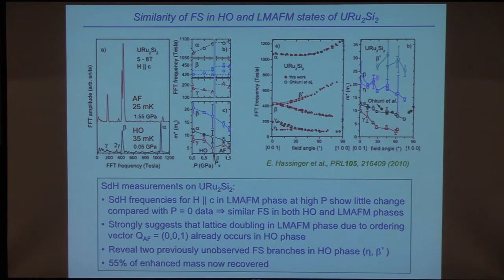Okay, now a few features about the hidden order phase. So these are some Shubnikov-de Haas measurements on uranium ruthenium-2 silicon-2 done under pressure. So this is in the hidden order phase right here. These are the amplitude versus frequency spectra. And this is in the antiferromagnetic phase, and you can see that they're not too different. And then when you look at the actual frequencies versus pressure, you see that they don't change much when you go from the hidden order phase at lower pressure into the antiferromagnetic phase at higher pressure. And then also the effective masses go through here rather smoothly. So this suggests that these two phases are rather similar, and some people suggest that one actually grows at the expense of the other as you go through this transition.